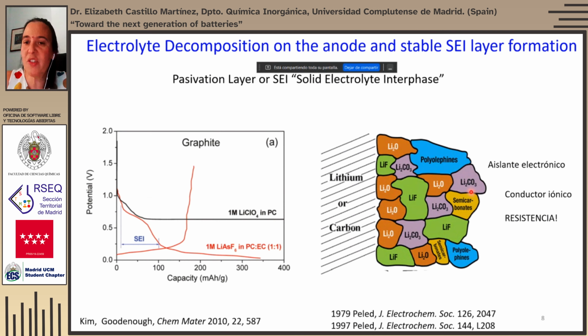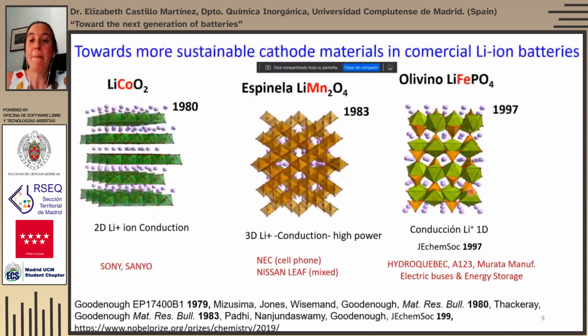Every time any new chemistry is developed, especially this high energy density alkali and alkaline earth chemistry. But as you can imagine, after the development of these commercial batteries, research didn't stop, but on the contrary, there was a lot of activity. And from the layer structured lithium cobalt oxide, there was a movement towards more sustainable cathode materials. So instead of using cobalt, which is mined in Congo mostly and in not very humanitarian conditions, let's say, other materials composed of manganese or iron as the transition metal, which are much more abundant and sustainable, have been developed.